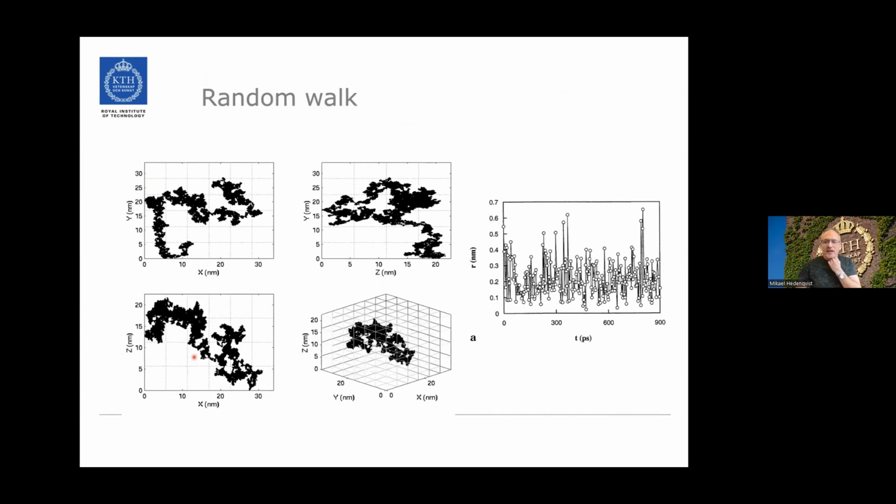And talking about long times, this is the trajectory of the limonene molecule as a function of time. We did the work up to 100 nanoseconds. In 2002, we did it on a PC, and it took essentially 1 year of real time to obtain these plots. So, 1 year. And here you see on the right a jump map, and this jump map tells us that the foreign molecule is doing a liquid-like diffusion.